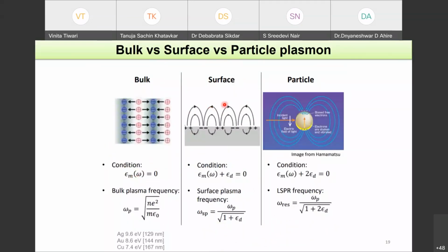Now, if you compare bulk, surface, and particle plasmons, what we saw is that the condition for bulk plasmon is where the permittivity becomes 0 at that frequency. That is the frequency of bulk plasmon resonance. Surface plasmon resonance, this is the equation, and for particle plasmon resonance, this is the equation. It means you can also obtain the bulk plasma frequency, omega p, omega sp, and omega LSPR.